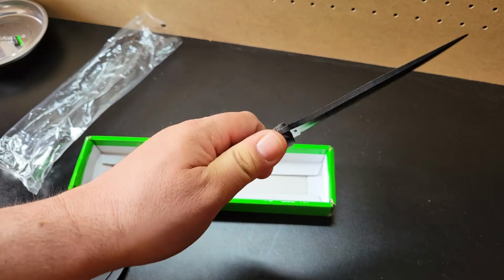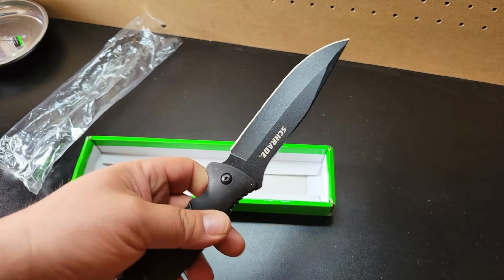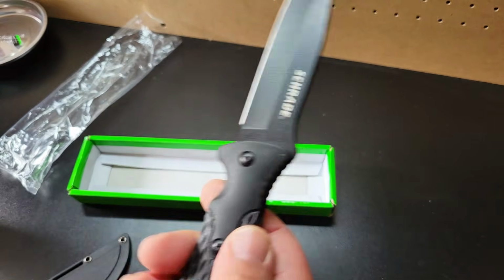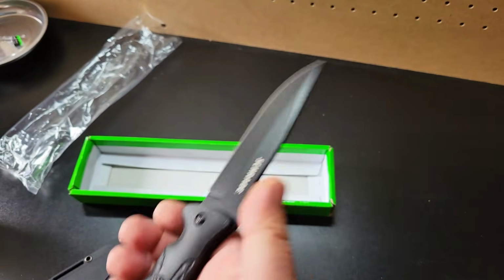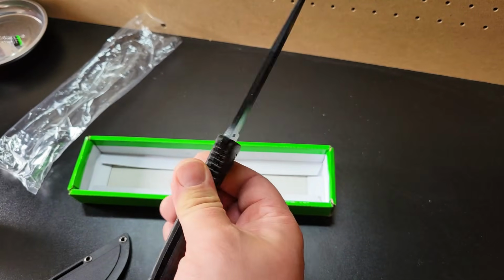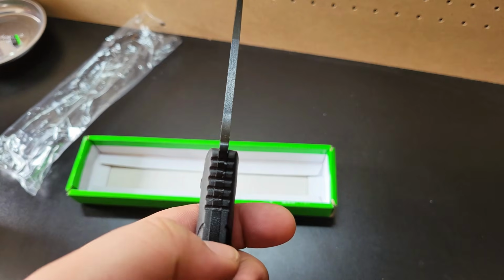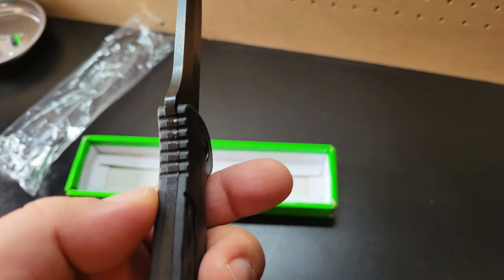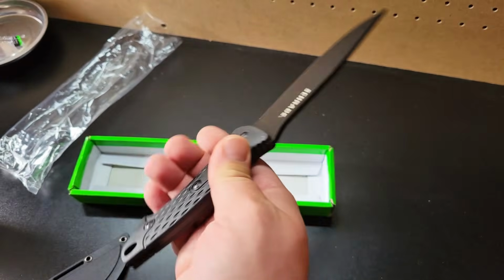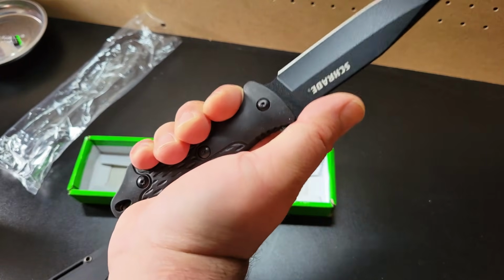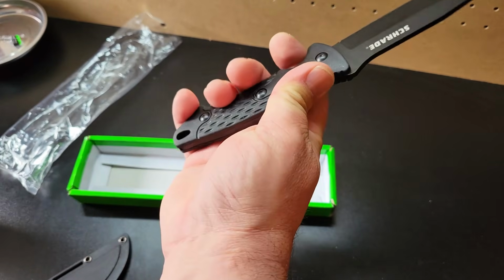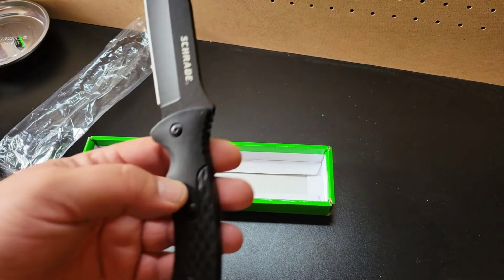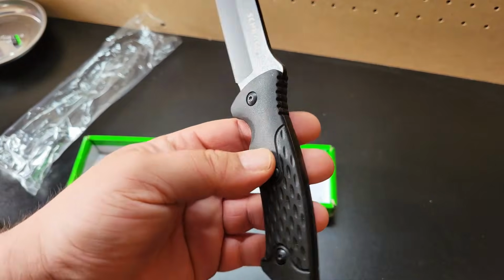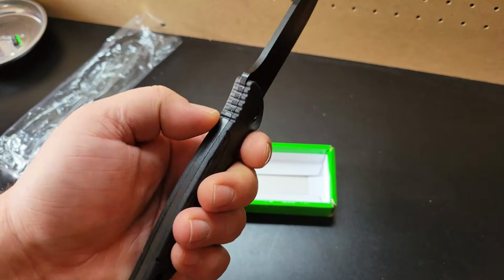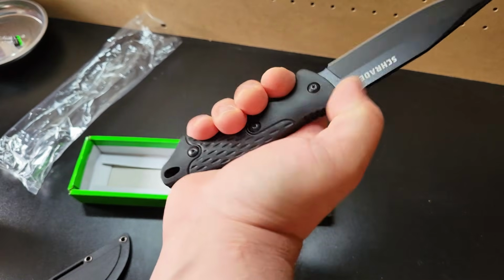The SCHF30's edge grind showed visible inconsistency on examination before testing began. The bevel angle varied across the blade length in a way that produced uneven cutting performance and created specific sections of the edge that were thinner and more vulnerable than the surrounding geometry. An inconsistent grind is a quality control failure that affects both performance and durability. And in the prying test, the stress concentrated at one of the thinner grind sections and produced a visible edge chip that required grinding to repair.